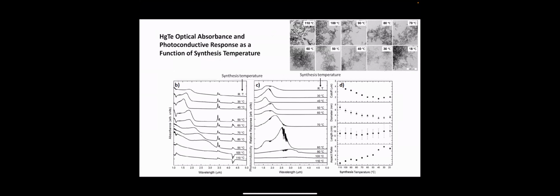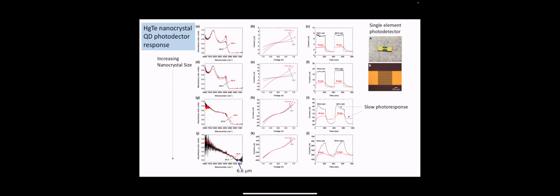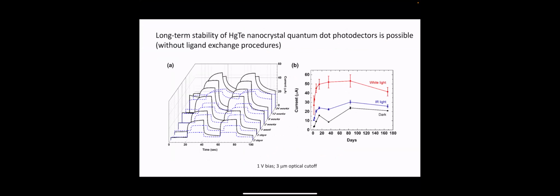photoconductivity response. So here in the bottom left, we have absorbance spectra, and in the middle is the photoconductivity response. And so even with nanocrystals with optical gap around 3.5 micron, 4 micron, you have a decent photo response. And so just getting into the far infrared is still a little bit challenging. But in the shortwave infrared, midwave infrared, with these tripods, these anisotropic shapes, we can get some really good photo response, and also stable over time.